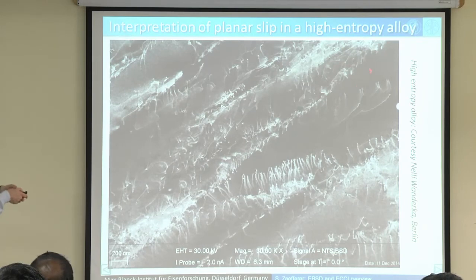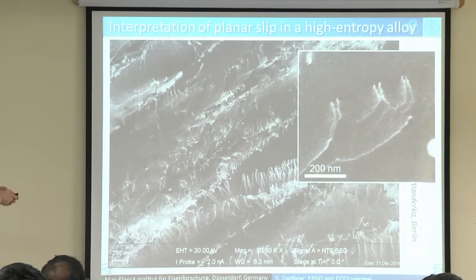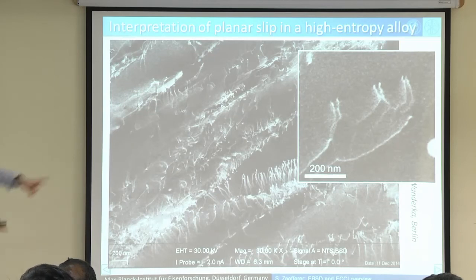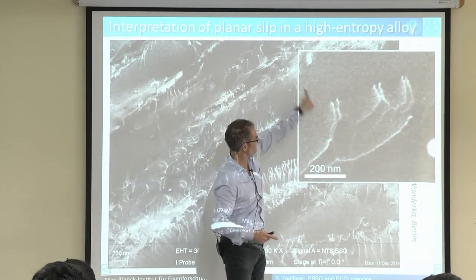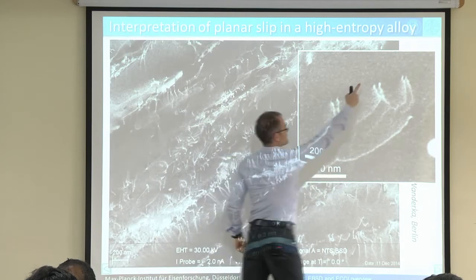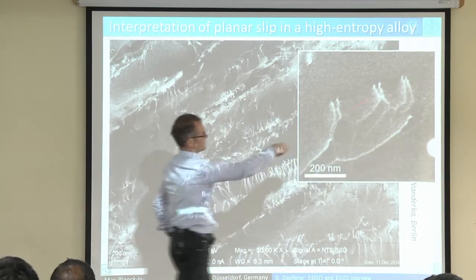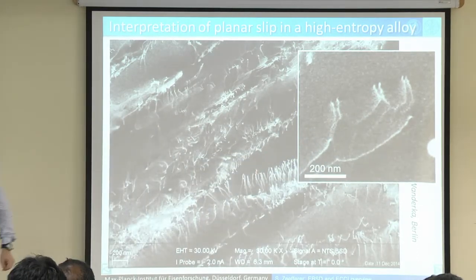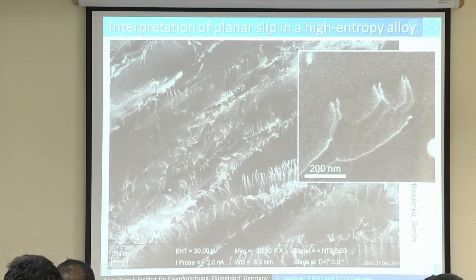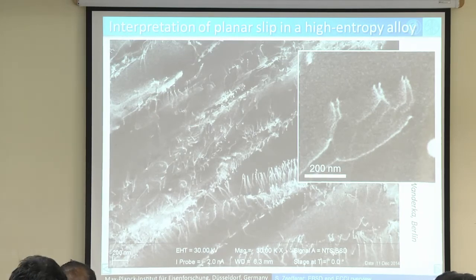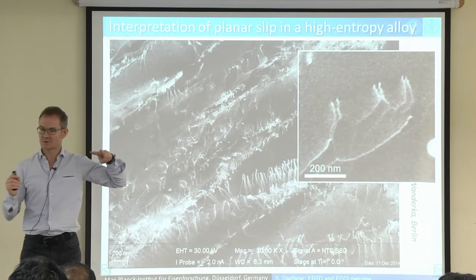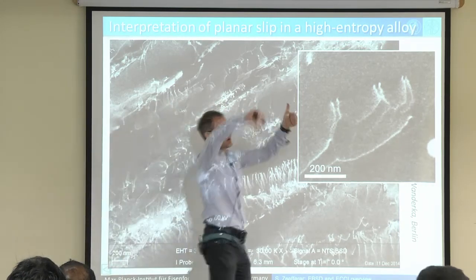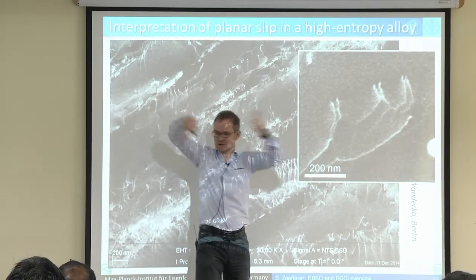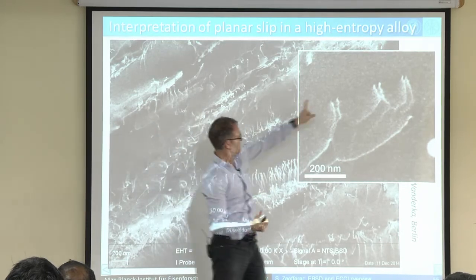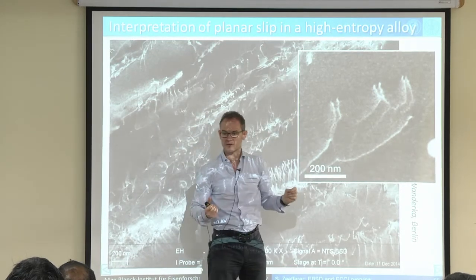What you also see here, if we zoom in, is that the dislocations are always grouped in pairs. And they have this typical oscillation. It's going this way, and you see always grouping in two. And this grouping in two could have two meanings. One could be that this is a dislocation dipole. So you have a plus dislocation and a minus dislocation, and they are coupled together. So this one would be plus, this one would be minus.